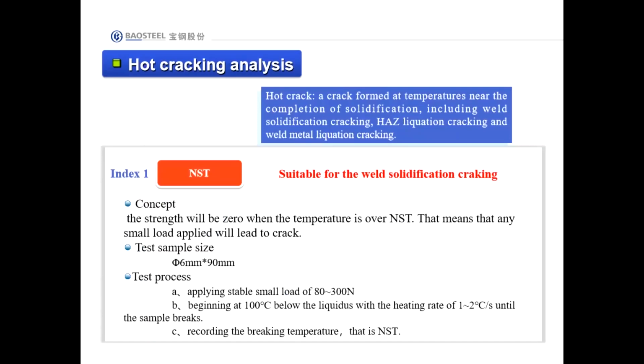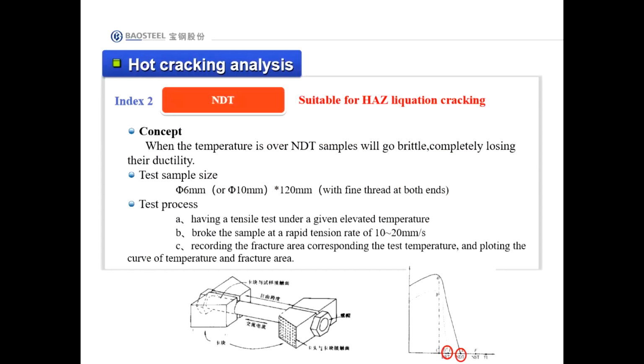The hot crack is a crack formed at temperatures near the completion of solidification, including weld solidification cracking, HAZ liquation cracking and weld metal liquation cracking. The NDT is also a good index for HAZ liquation cracking. When the temperature is over NDT, samples will go brittle, completely losing their ductility. Here, I don't introduce the experiment process.